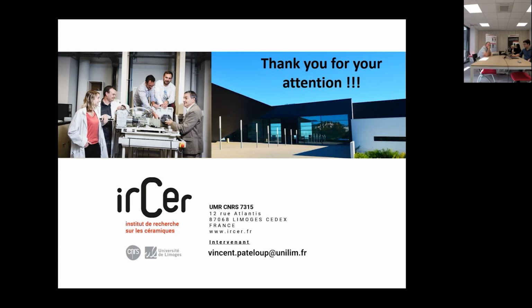Next question is, what about the overall shrinkage of the parts? I guess it's the same as for SLA. Yes, concerning the substrate, it's the same as SLA, about 20%. And for the metal one, it depends on the charge of the metal paste at the beginning. For example, for tungsten paste, we have put inside the tungsten paste a little quantity of alumina in order to have a nearer dilatation coefficient. Yes, something like this. Okay, that answered the question.